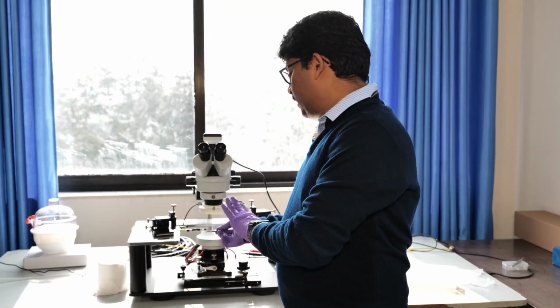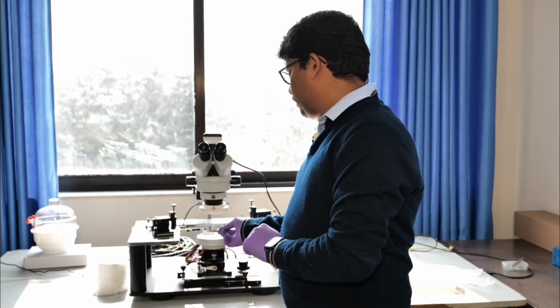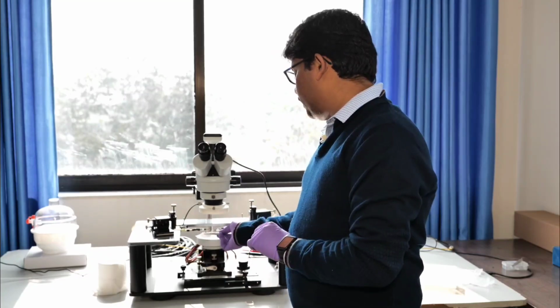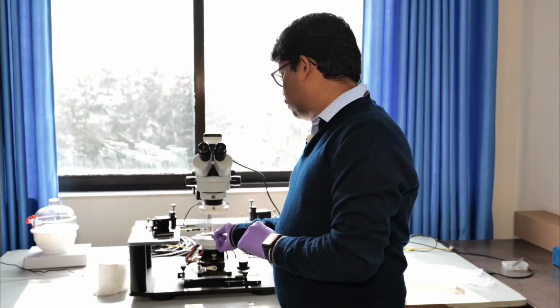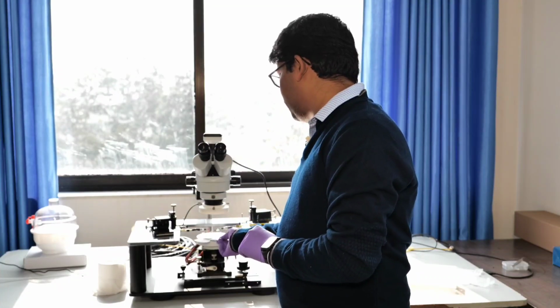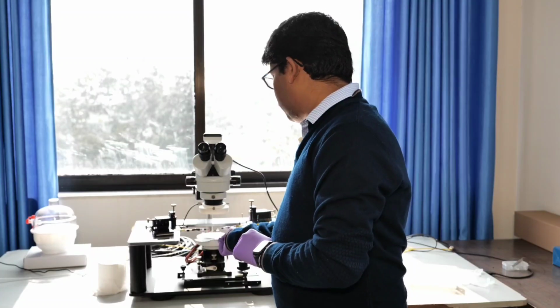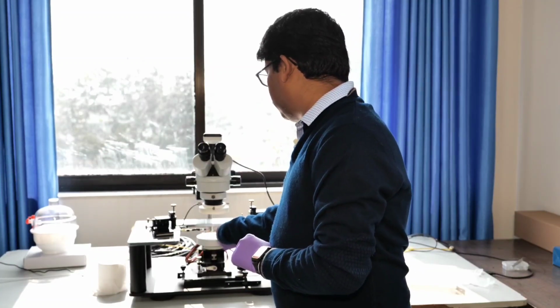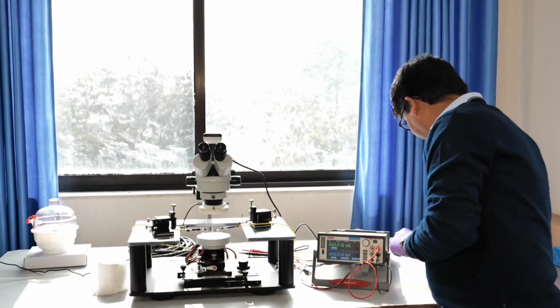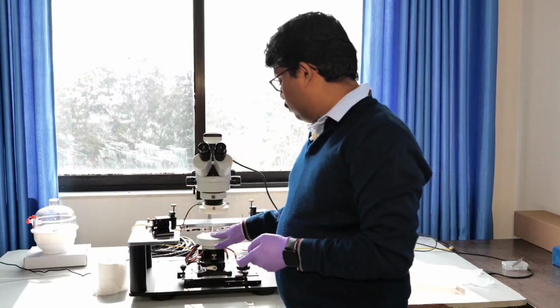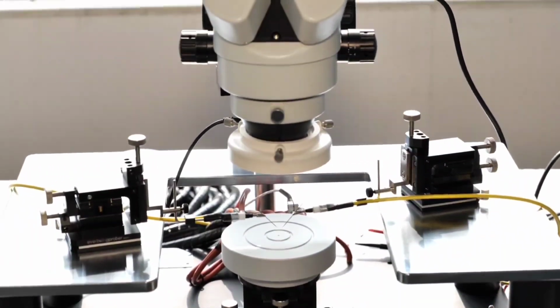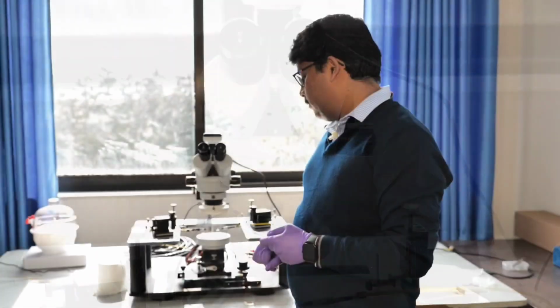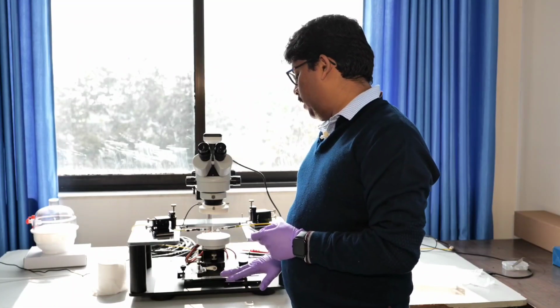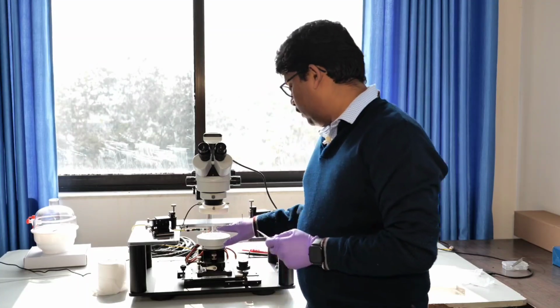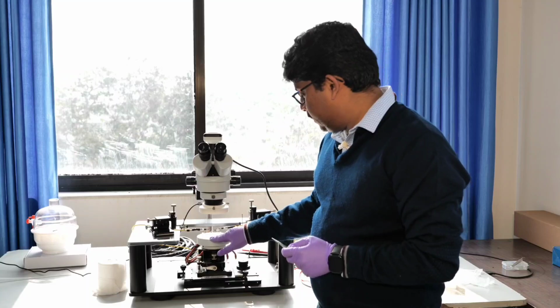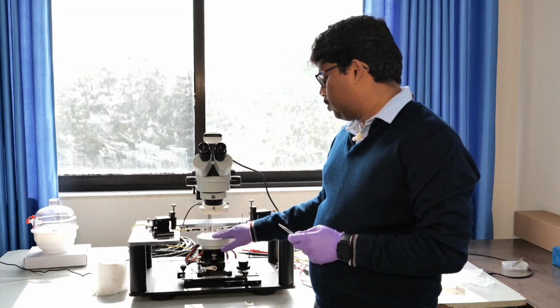Here we do not have any gallium oxide or Sn-doped gallium oxide thin film grown. But during that experiment we grew those gallium oxide films on this kind of sapphire substrate, and we fabricated devices, and after fabricating the devices we used this kind of probe station. Here these are the two terminals. As I mentioned, we could fabricate simple two-terminal Schottky barrier diodes where we have one anode and another cathode. These are the probe tips, and this is called the chuck,